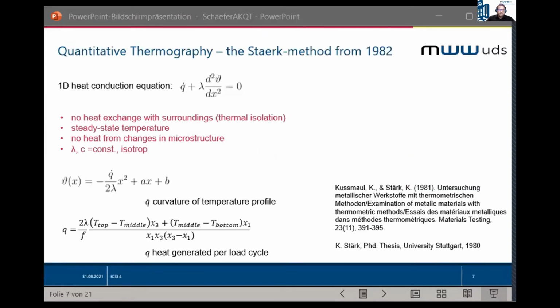So if we now use these NTCs, we have a very low budget, but a very high effort method, because we need to measure the temperature at 3 distinct points on the sample along its parallel length. The idea is to measure the curvature of the temperature profile with just 3 sampling points, because the curvature characterizes the heat generation inside the material.